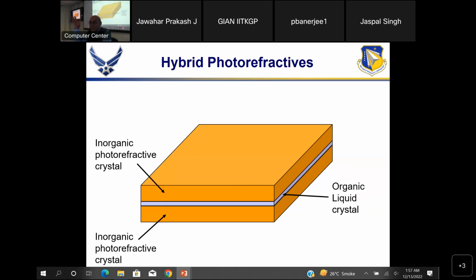Okay. With any kind of electro-optic material, you have to apply hundreds of volts, depending on the thickness, of course, because it depends on the electric field. But finally, the change of refractive index is typically a small number, like 10 to the minus 4, 10 to the minus 5. That's the typical. These are things, by the way, physics or no physics, doesn't matter. In practical life, try to remember some of these numbers.